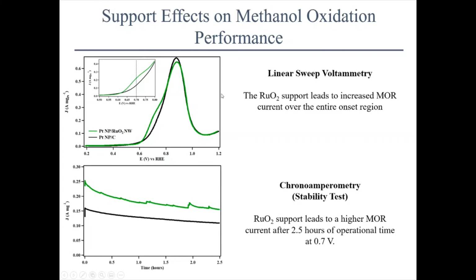Another way of looking at this is we can take our catalyst and send it up to a potential in this onset region, and then look at how it oxidizes methanol over a period of time, like 2.5 hours. We call this chronoamperometry. And what we saw was that the current density over the entire oxidation window of 2.5 hours was higher. And you can see this little sawtooth pattern that was happening.